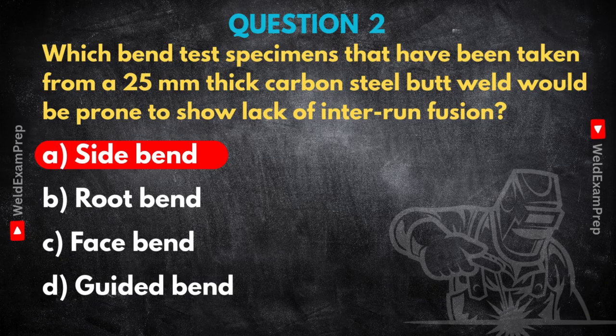Pretty much. Now, in a thick weld, like 25 millimeter, you've definitely got multiple passes, one layered on top of another. A side bend specimen is cut through the weld thickness, so when you bend it, you're putting stress right across all those layers. I think I see where this is going. Yeah. If there's a lack of fusion running along the length of the weld, sort of parallel to the surface but buried inside, the side bend test forces that area open. It exposes those internal flaws beautifully.